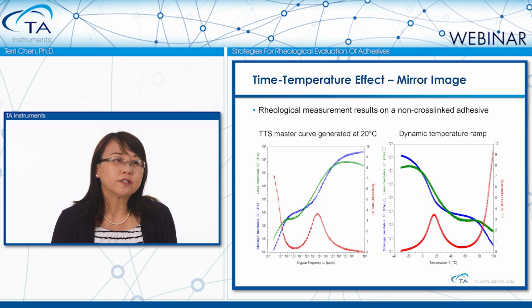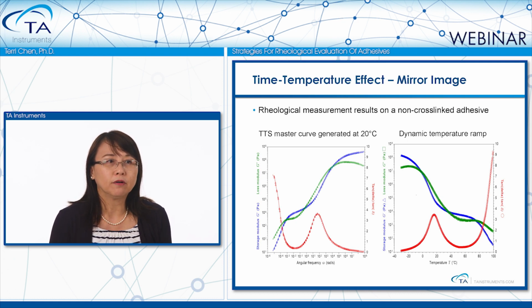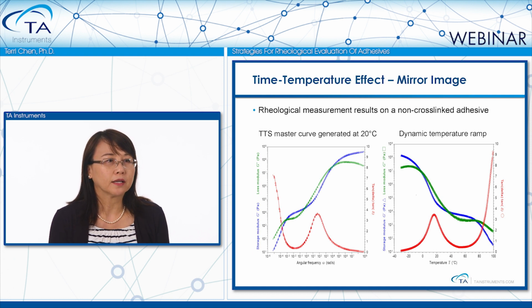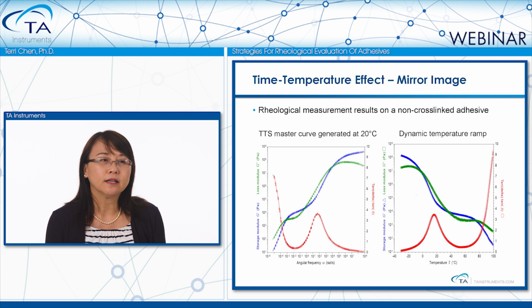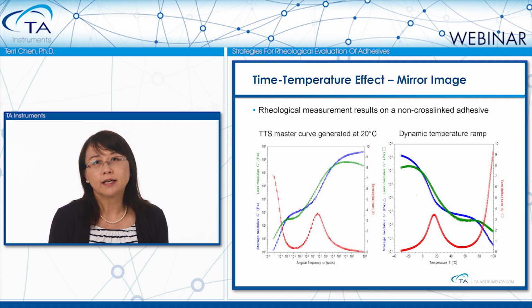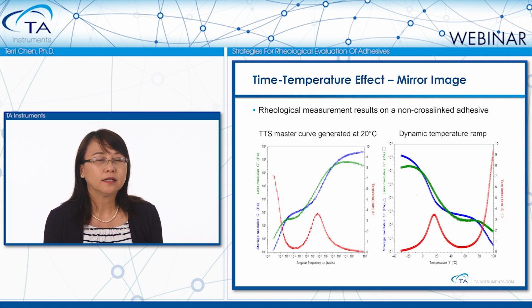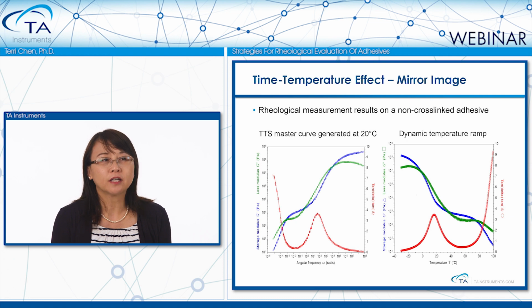The figure on the left side of this slide is an example of TTS data on a non-cross-linked PSA sample. The reference temperature was selected at 20 degrees C. If you put this TTS master curve side by side with the dynamic temperature ramp data, you will easily see that these two results look like a mirror image. This is the principle of the time-temperature effect.